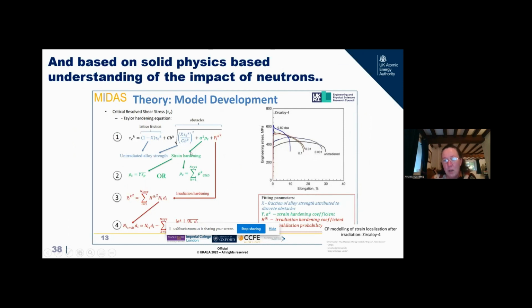So we are working with algorithms where each of the terms represents something like strain hardening, irradiation hardening coming from the neutron impact. And we are validating these terms through small micromechanical experiments. And we're doing this for one slip system and then another slip system. And then we've created solvers to combine the slip systems. And we've created software to produce three-dimensional microstructural proxies, so that we can start to say, yes, we could actually predict that that will move to that with that amount of damage.